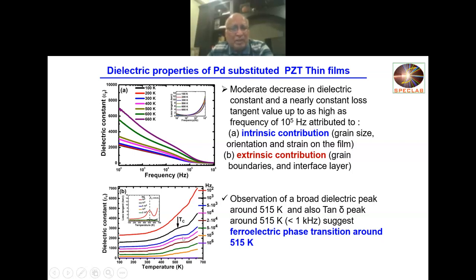From the thin film case, in the ceramic case, we could not get the transition temperature, but here we can see a peak occurring around 515 K. So in thin films of PZT-PD, there is a definite phase transition, that is a ferroelectric transition, around 515 K.